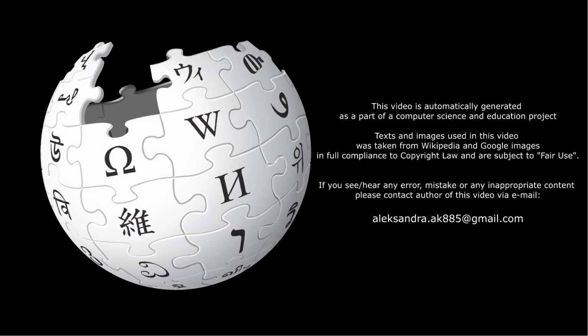Hydrogen silsesquioxane, HSQ, is a negative tone resist that is capable of forming isolated 2 nanometer wide lines and 10 nanometers periodic dot arrays, 10 nanometers pitch, in very thin layers. HSQ itself is similar to porous hydrogenated silicon oxide. It may be used to etch silicon but not silicon dioxide or other similar dielectrics.